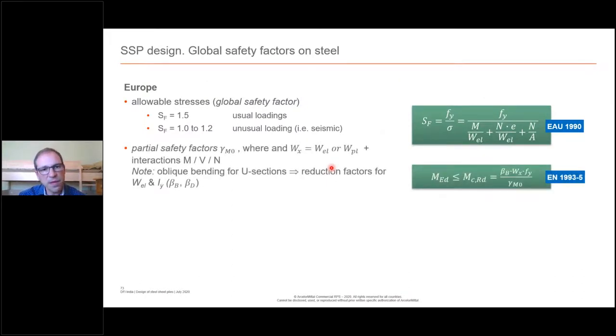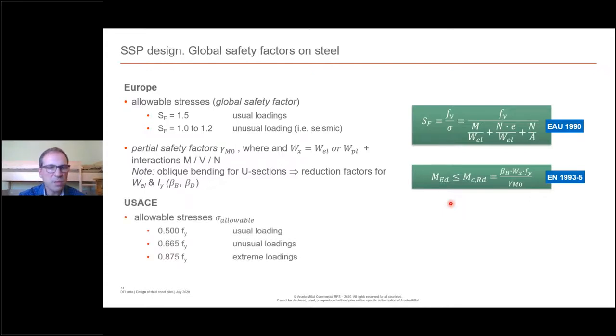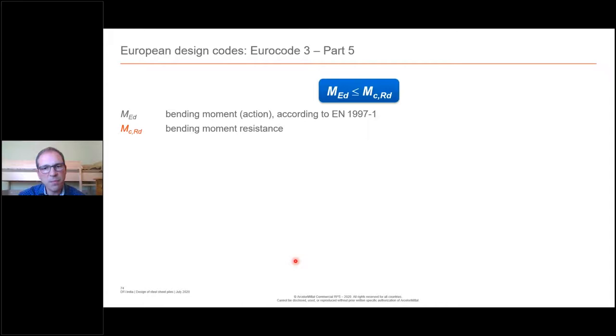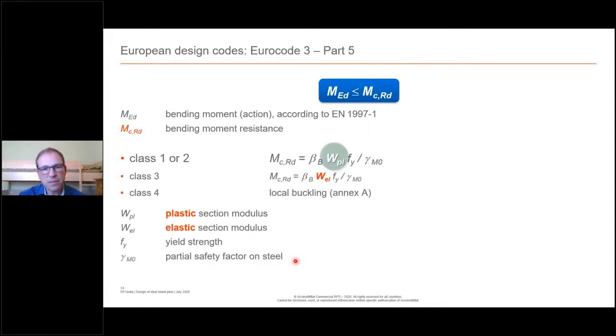So in Europe, in the past, we used the allowable stress method with a global safety factor. But nowadays, it's the formula that you see here, where we have partial safety factors, which are the gamma M0, and then reduction factors that take into account specific features, like for U-piles, where you have to use these reduction factors. And in the United States, they also use reduction factors, but they make the distinction between usual loading, unusual, and extreme. And even in France, for instance, they make the distinction between temporary and permanent. So they don't use the same safety factor if it's a temporary structure or if it's a permanent structure. But important is not to mix the methods.